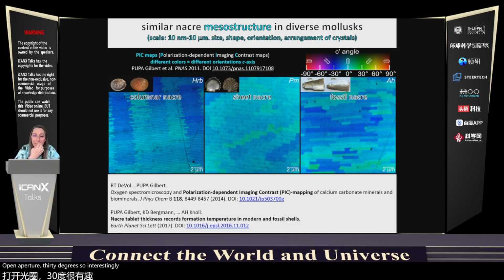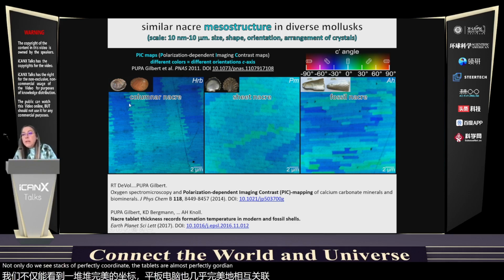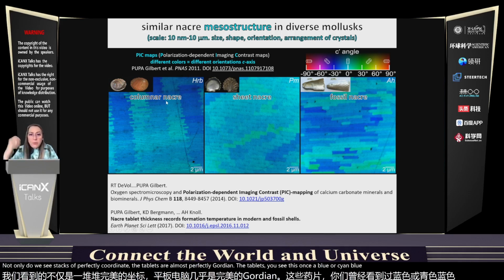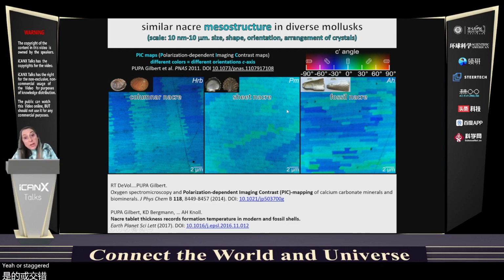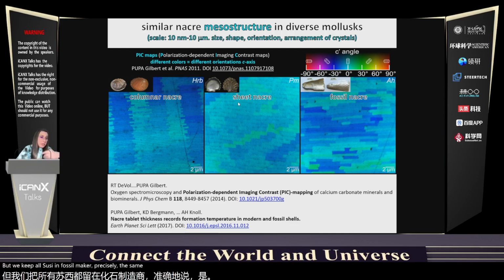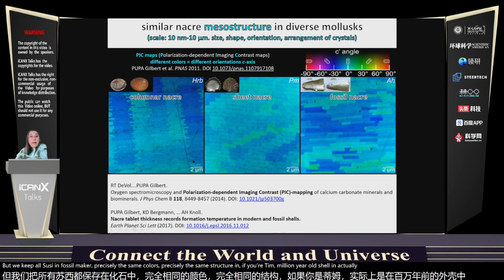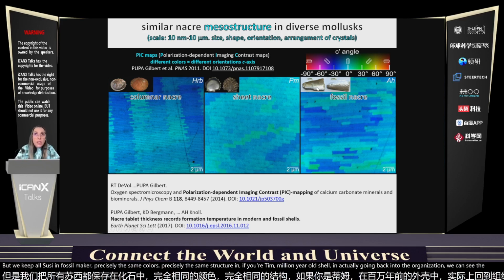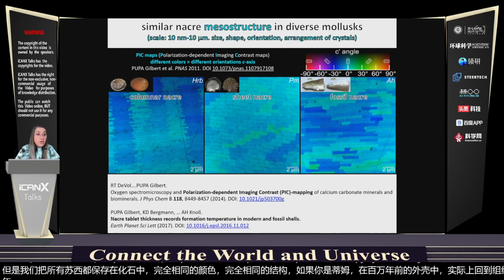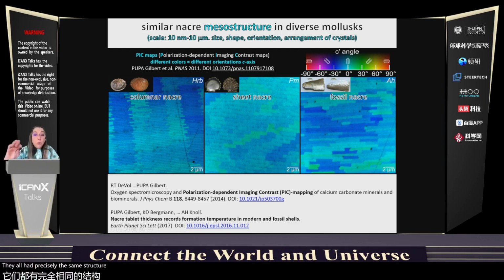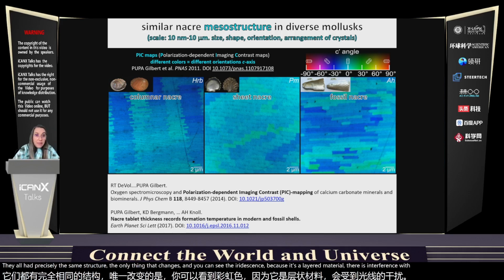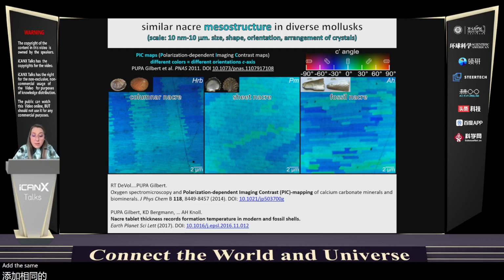So interestingly, not only do we see stacks of perfectly, or almost perfectly, co-oriented tablets, with blue, cyan, blue, cyan, blue, cyan staggered diagonally in sheet nacre, but we can also see in fossil nacre precisely the same colors, precisely the same structure in a 13 million year old shell. And going back into the Ordovician, we can see the earliest formed nacre, 450 million years ago. They all had precisely the same structure. You can see the iridescence because it's a layered material, there's interference with light, exactly the same way in the modern and the ancient.